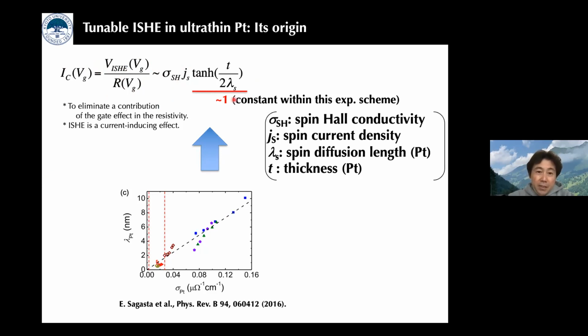But in our case, this tangent hyperbolic term can be regarded as unity. Because of this, a group in San Sebastian, Spain, reported the conductivity dependence of the spin diffusion length of platinum: when the platinum is resistive, the spin diffusion length is largely suppressed. Because of this, we neglect this term in our discussion.